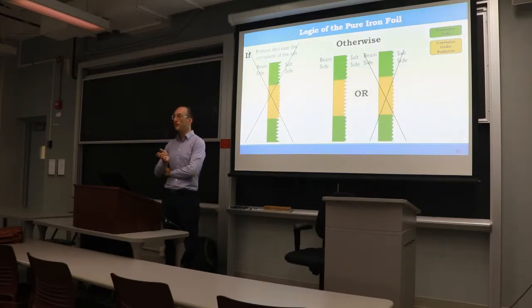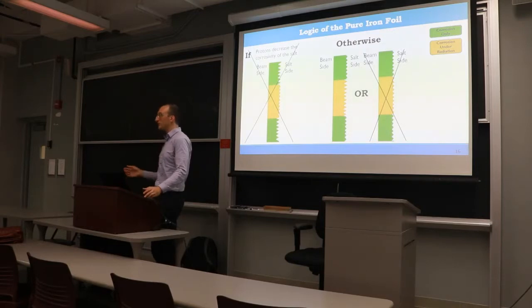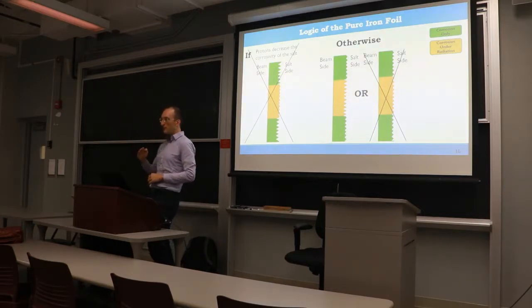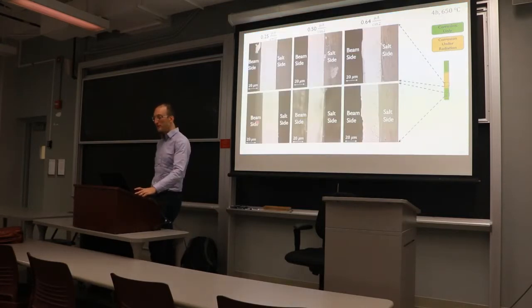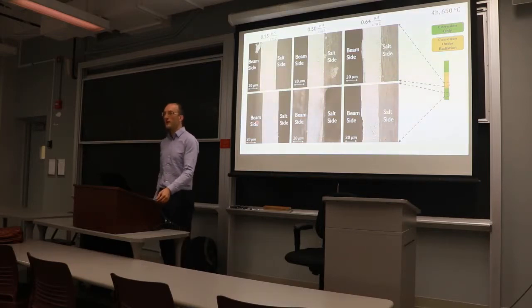Which would be equivalent, though, to using a slightly thicker foil. Because what matters then to me is what is the damage level or the proton beam energy at the edge of the foil that's facing the salt. So we can make slightly thicker foils. But our goal is always to make sure that the protons pass way through the foil and end up in the salt. There's also activation concerns, which at 3 MeV, they're just starting to pick up. And if we went to 4 or 5, things would get very toasty. We'd make a lot of neutrons. Right now, we have to let things cool down for about 4 days. And that's acceptable. Any more than that, and things would get slow again.